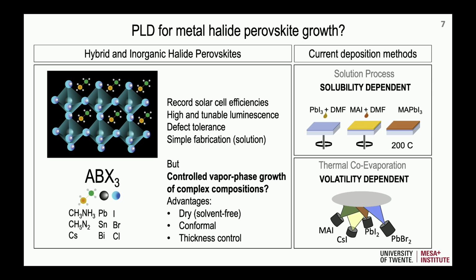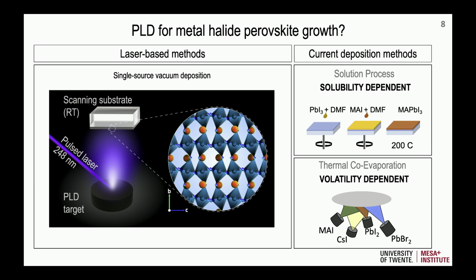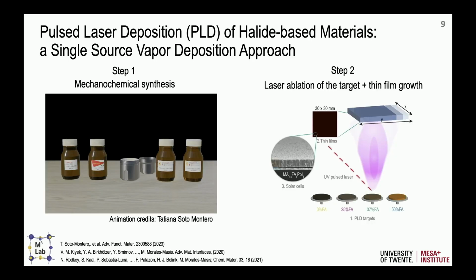And finally, thickness control. So the proposition that we had when I started the group in Twente was, okay, we have these current methods, we can go for laser-based methods as a way to overcome the volatility dependence and the solubility dependence. So get rid of those 2 challenges by using, instead of thermal sources, a laser that basically uses thermal and non-thermal processes that can ablate your material. So how do we do it?